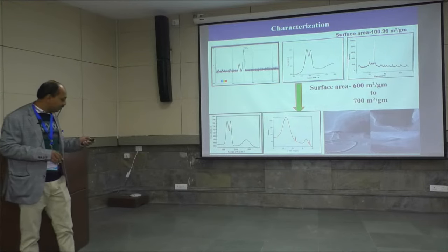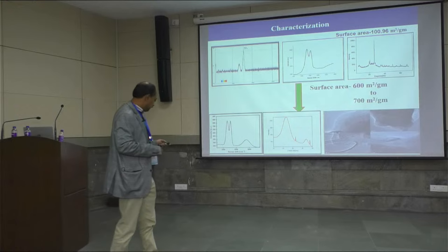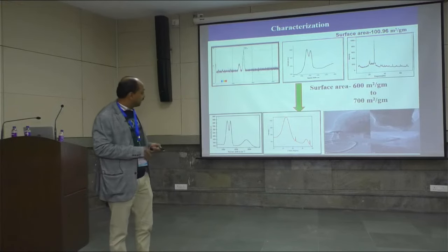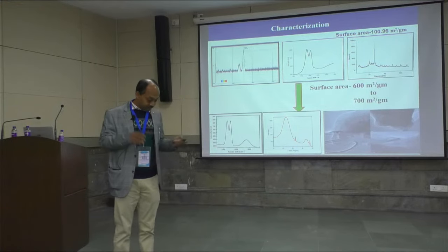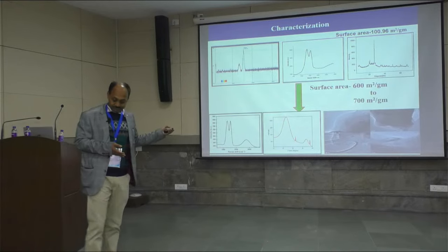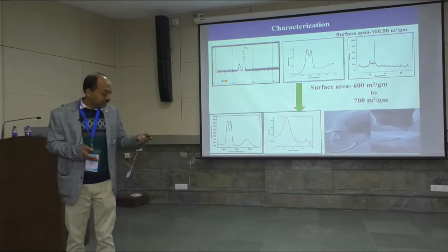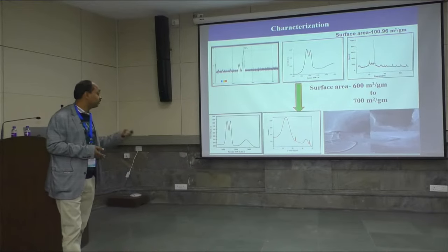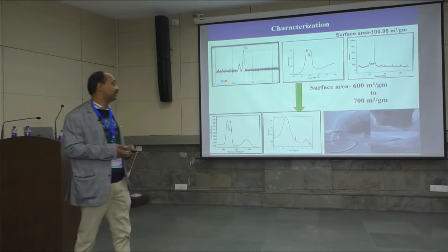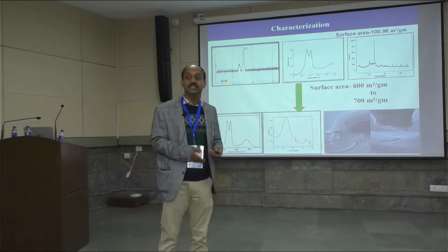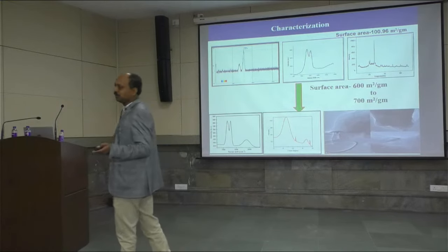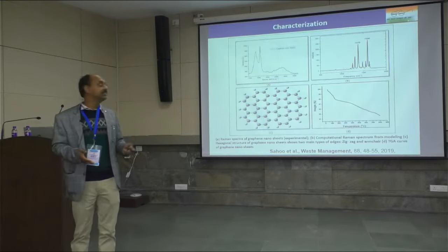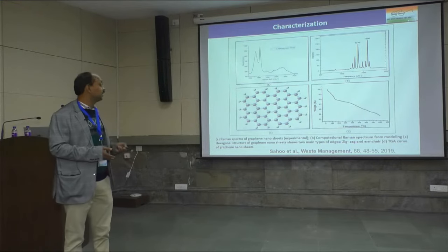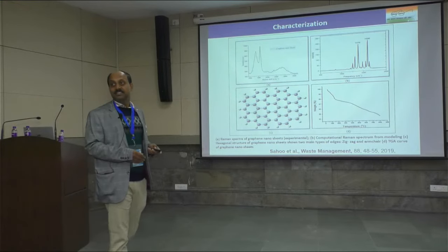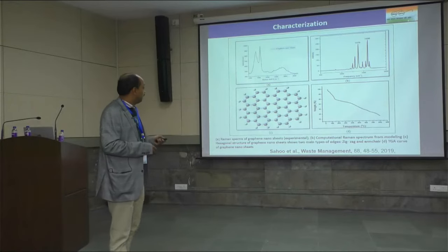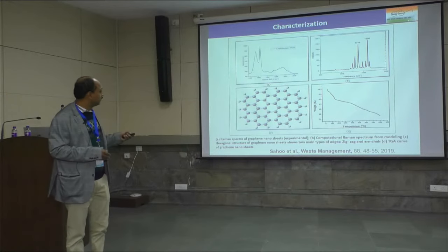Anyhow, now we are getting knowledge from the Raman and XRD, SEM and also TEM and also the AFM. We can say that from this graphene we are getting a surface area of near about 600 to 700 square meters per gram. So in about 3 to 4 years of graphene work you can see this, and these studies were done by Dr. Sandeep sir, and we have also published a paper.